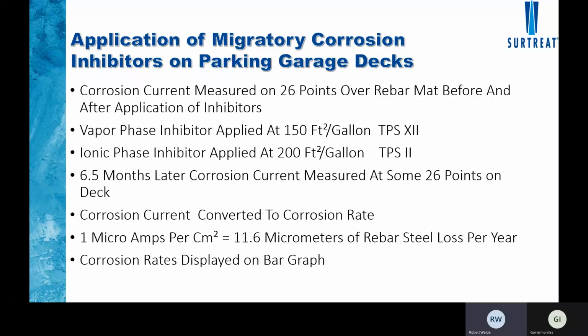Here's a little example. This is probably one of the most important things we're going to talk about today, how we actually go out and make application of our corrosion inhibitors in an actual structure, in this case, decks of a parking garage. And what we did, before we did anything, we went and mapped out 26 points over the rebar mat on the deck of the garage. And we made corrosion rate measurements there. We then applied our two corrosion inhibitors. We applied TPS-12, the vapor phase inhibitor, at a rate of 150 square feet per gallon, which is the standard method we use for measuring application rates. We next applied TPS-2 at 200 square feet per gallon.